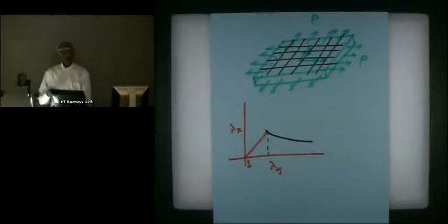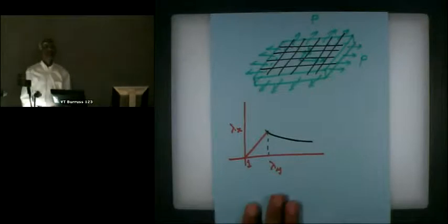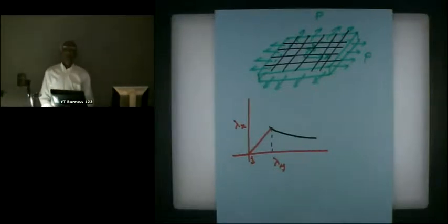So it can happen that if you are applying equal loads in both directions to a square piece of membrane, meaning it's very thin in the thickness direction, then after a certain while, the two stretches become unequal. I cannot tell you whether lambda x will be more than lambda y or lambda y will be more than lambda x. None of us who studies this kind of problem can tell in advance. However, this you can see in experiments. So it's not something I am cooking up.